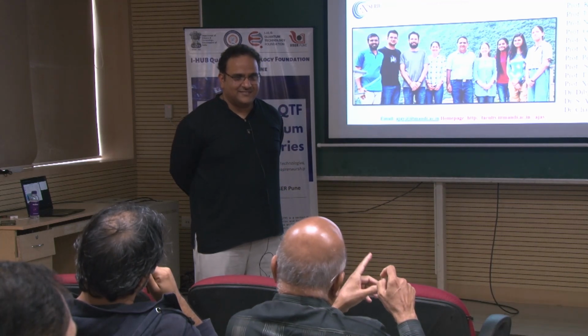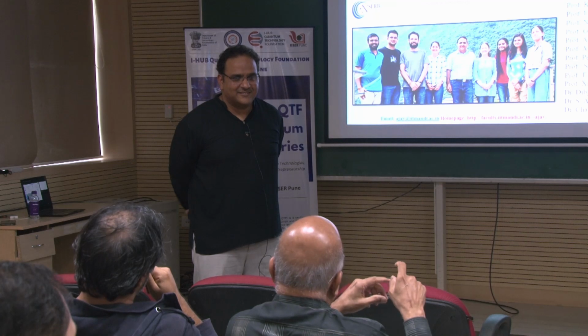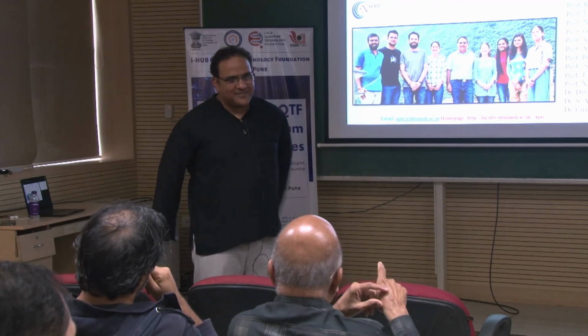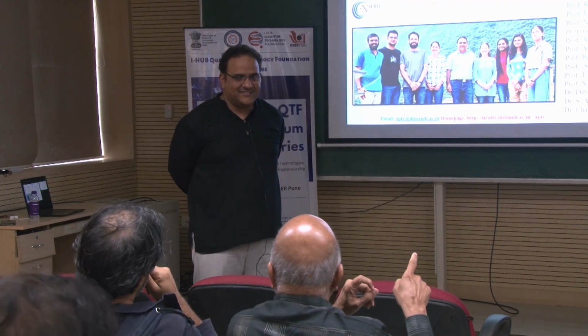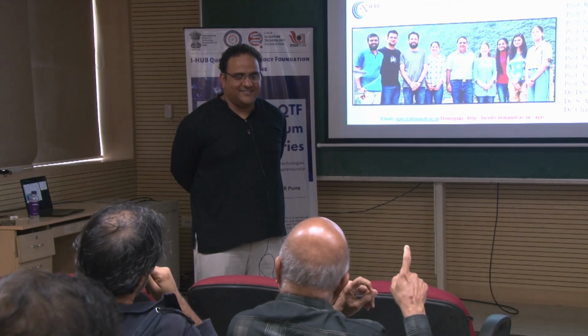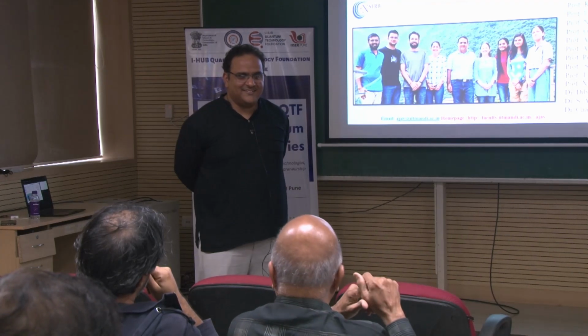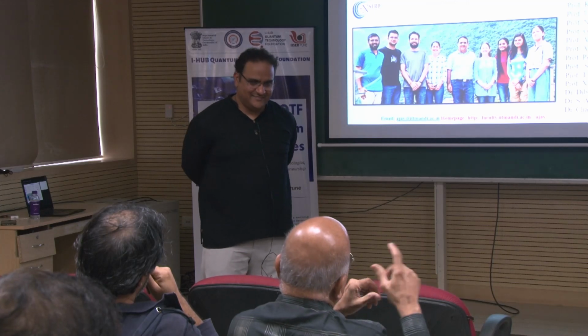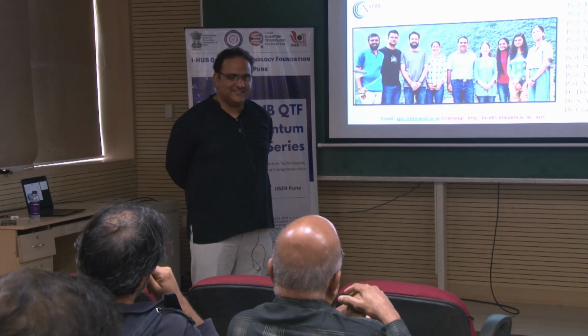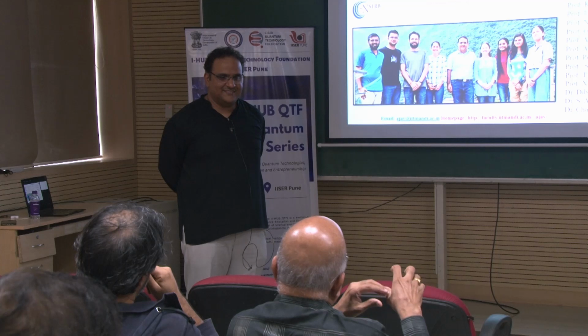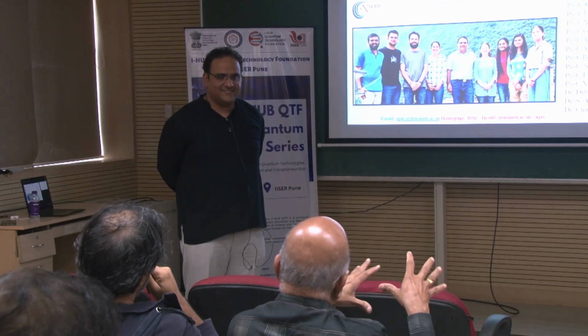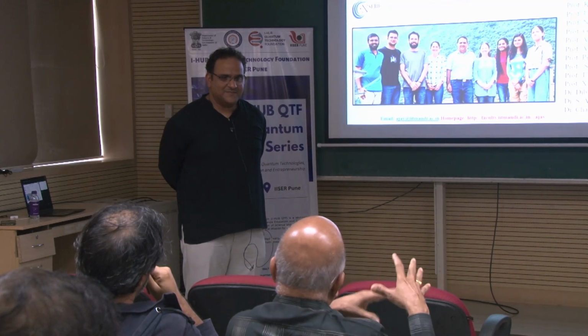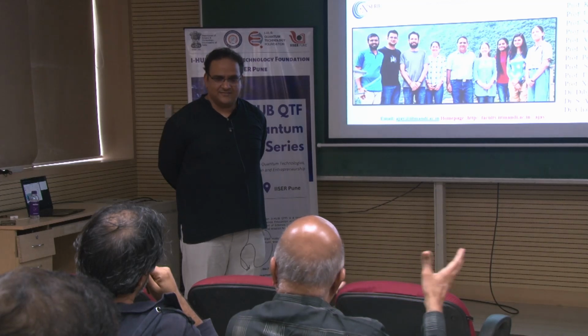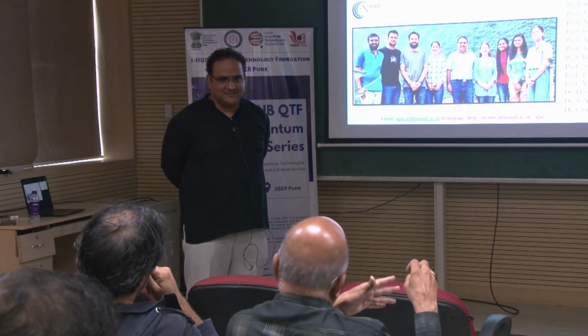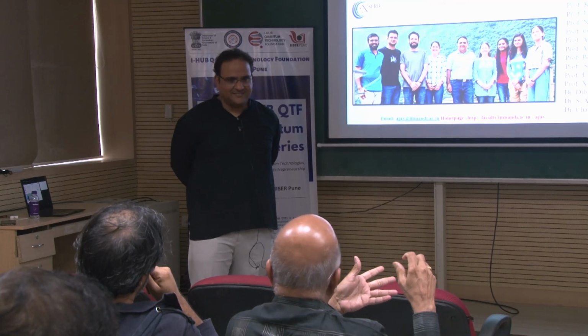So I think titanium ditelluride is probably a smoking gun proof for your technique to show that it is really these modes which are bringing out the CDW in this. Yes. And so is niobium disulfide. See, there are some measurements which show that there are local CDW traces in these materials. But people have not... niobium disulfide also doesn't show CDW, but the thin films have this effect there.